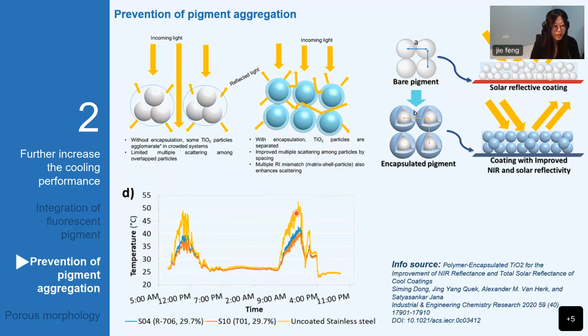Secondly, it is well known that reflective particles in coatings tend to aggregate. The aggregation of particles not only reduces light scattering efficiency due to the overlapping of the particles, but also adversely affects other physical properties of the material. In a very recent study, cool coatings formulated using polymer encapsulated particles resulted in an improvement of up to 10% of the total reflectance, and therefore can improve the cooling efficiency accordingly.